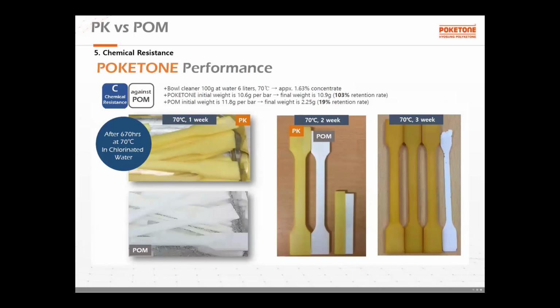Another one, the low acid chemical resistance for polyketone. Bowl cleaner in restroom, for the water 6 liters, 70 C temperature, that means concentrate 1.63%. And after 70 C for 3 weeks, polyketone mechanical property is almost 100% for the retention rate. But you can see this shape here for the POM, 19% only.